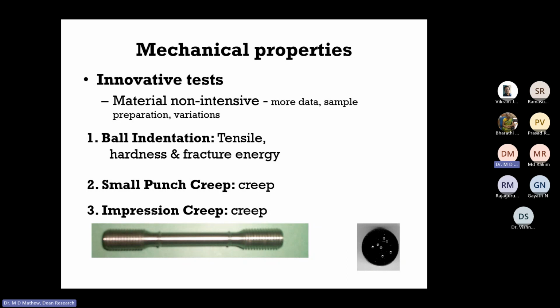So this becomes useful in the case of structural integrity evaluation, which means you can scoop a small portion of the material without compromising the integrity of the component. You can scoop out a small piece, and that can be used for these kinds of tests. And of course, the scooped portion, you can do some weld overlay and repair it.